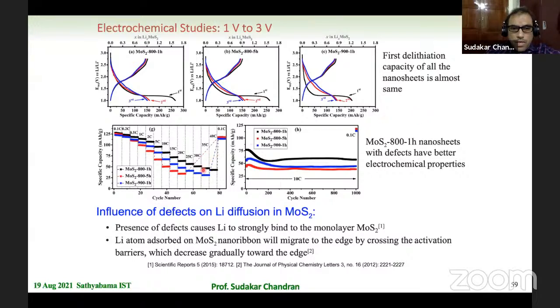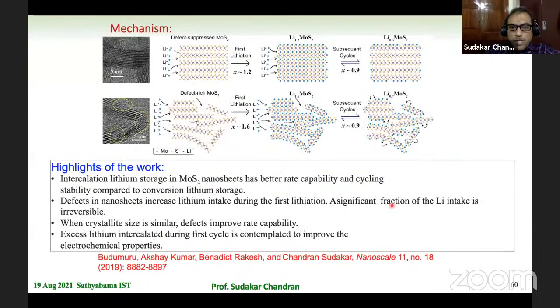So in this particular case, what we found is that the 800 degrees Celsius 1 hour sample exhibits a large C rate. For example, you can cycle at 40 C rates. Even at 20 C rate, a large chunk of capacity we could see, which means the nanosheets can be used for high C rate applications. But of course, the temperature has an effect. Too much ordering also helps to some extent with high rate capability. But we found that an optimum condition of both the presence of defects as well as the crystalline nature is important, because one supports the rate capability, the other supports the cyclability, and therefore you need an optimized condition in order to get the best electrochemical properties.